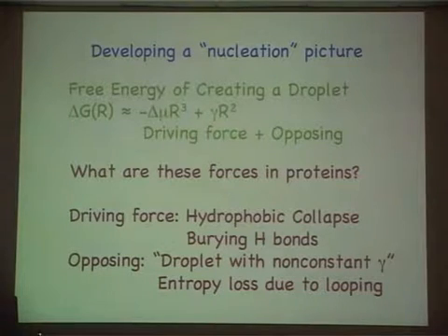For reasons that were pointed out yesterday, which become even more severe when I pose this in the context of protein folding, none of these numbers, in fact, are constant. We don't know exactly what the driving force is. Certainly, surface tension is not really a constant, and these are problems that exist in writing down something as simple as that. Even in the homogeneous nucleation theory, we knew from yesterday that to assume that these droplets are spherical is not correct, and in fact, there are fractalities associated with that one must worry about in the context of protein folding even more.